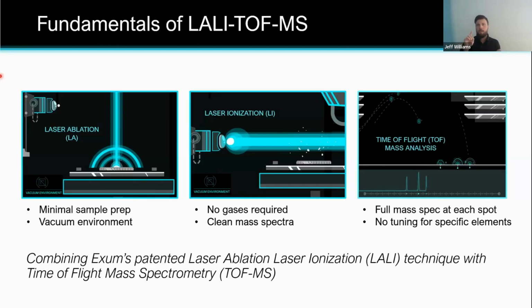And because it's in vacuum, and because it's a mass spectrometer, we're literally measuring the ions that we are liberating from the sample surface, or the atoms, to the detector. We're going to know exactly for sure that it is that element, because we can get a very clean mass spectrum with isotopically correct signature to say, yep, that is definitely lithium, it's definitely chromium, iron, and so on and so forth. And our software is going to handle all of that identification of those elements for you. And we don't have to worry about a lot of interferences like you might have in spectral or even other mass spec spectra. It's very clean, isotopically correct, with every single element showing up at every laser shot.